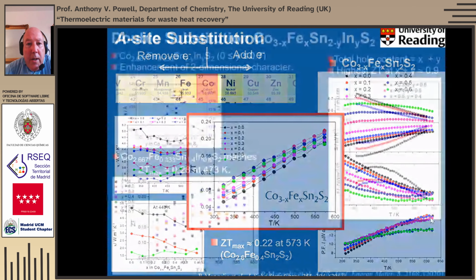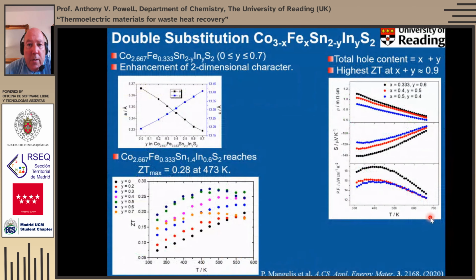And then, of course, we can combine those two features. We can do substitution of both the transition metal and at the main group cation site. What we find when we do that is that we seem to enhance the two-dimensional character of the material, because what we see is quite a significant increase in the C lattice parameter, for example, and we can push our maximum ZT up to about 0.28, but at a relatively low temperature. This is only 473 Kelvin, so that's quite a good value of the figure of merit at that temperature.